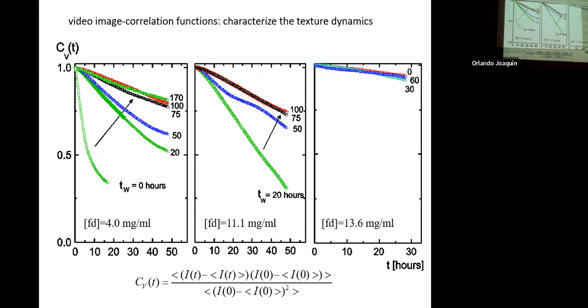It's in an equilibrium system. This is at 11.1, so just below. You see the same thing, a relatively steep decay even after equilibration - so the texture has its own sort of dynamics. But then at the robust glass condition, starting from time t=0, they are all the same, and there's a kind of aging if you like, but it doesn't involve time anymore - it's independent of the waiting time.